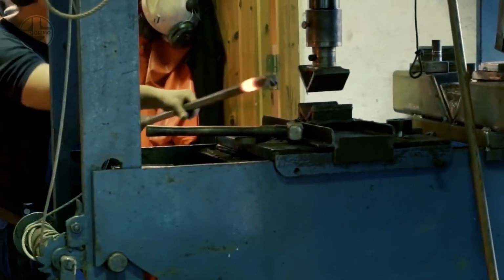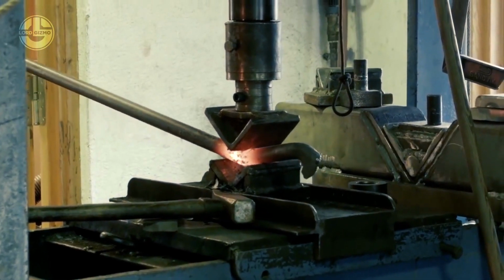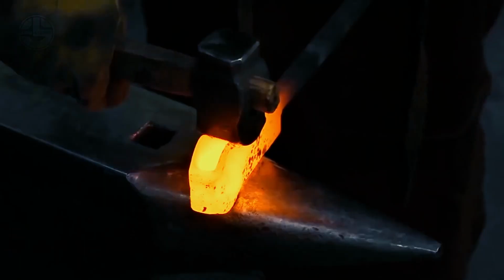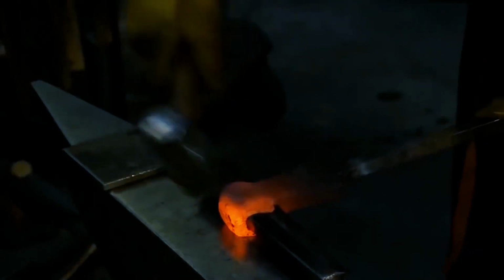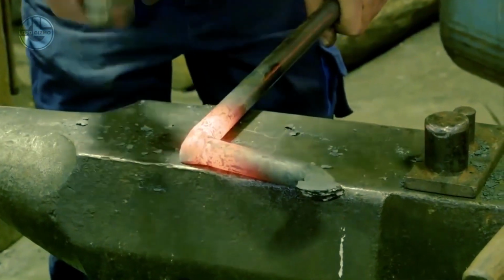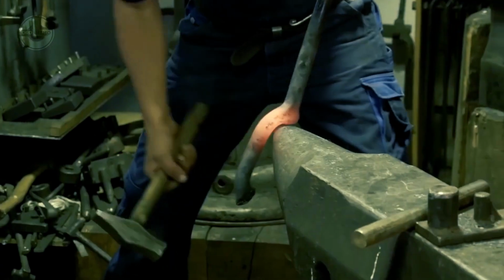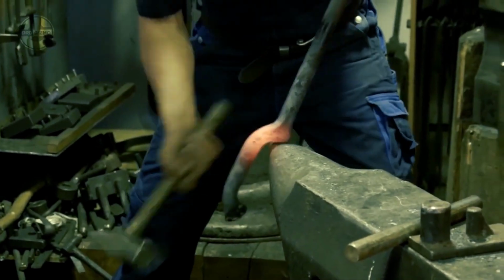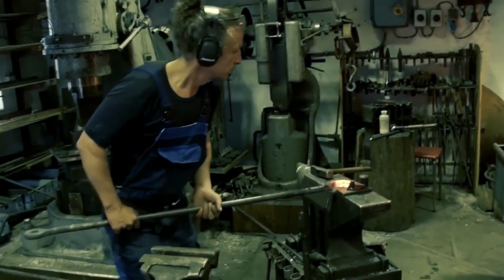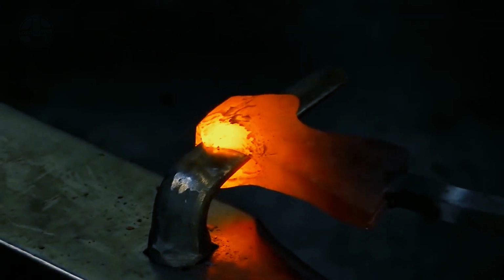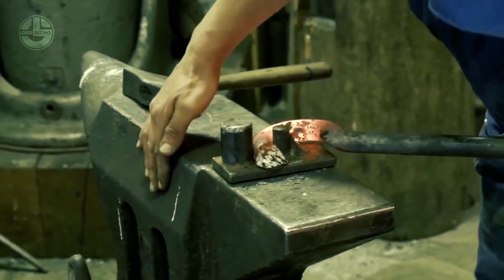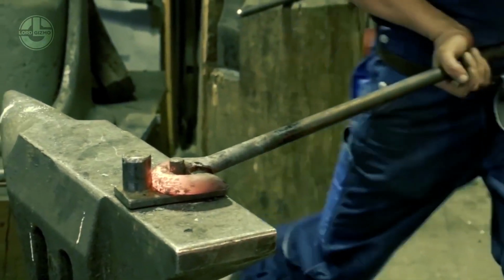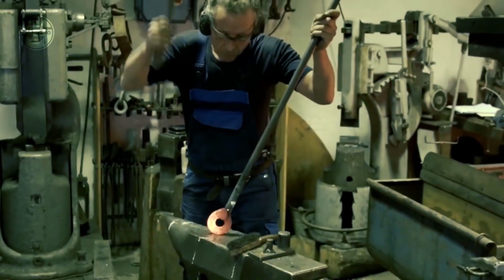Before, manual hammering was used in this process. Once the metal is heated and has reached the target temperature, it will be coated in flux. The joint is repeatedly struck by a handheld hammer so the weld surfaces can overlap and join each other. The flux is able to flow out thanks to the hammer blows and the joint's actual creation, which involves beveling or rounded surfaces. To prevent the flux from blasting out of the joint as soon as the initial blow is struck, the hammer blows should only be fairly hard.